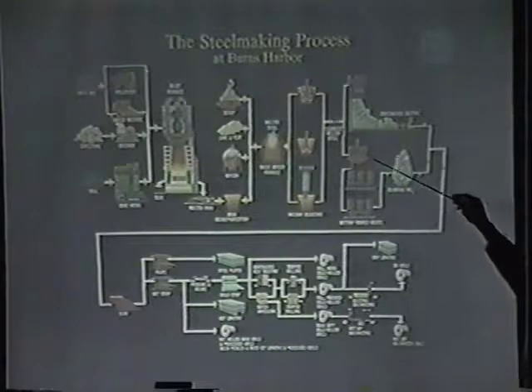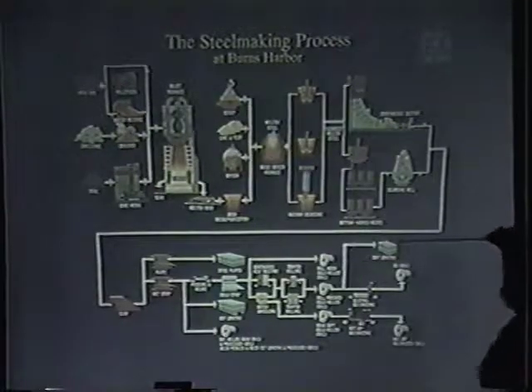That ladle will then have the steel refined. We can argon stir that steel in the ladle. We can vacuum degas that steel. We can desulfurize, take some of the sulfur level out of that steel in the ladle, and so forth. But once we have refined the steel in the ladle, it goes to either our continuous casting process or into our teeming aisles, where we're going to make a slab. The entire top half of this chart is our primary side of steelmaking. This is what we're going to cover this morning.